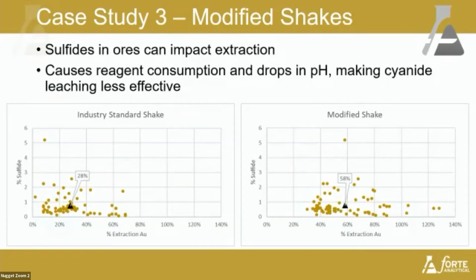What we've done here is an industry-type standard shake. It was 15 grams of material, 2 grams per liter cyanide, adjusted to 10.5 pH, run for 24 hours on an orbital shaker. That's your left-hand industry shake. We got an average of 28% recovery for gold for this data set. We recognized later, when we tested the pHs afterwards, that they were very low. So we obviously had some sulfide material in there or something else that was consuming our lime reagent.